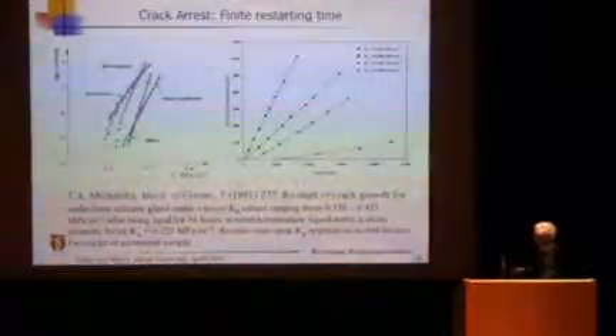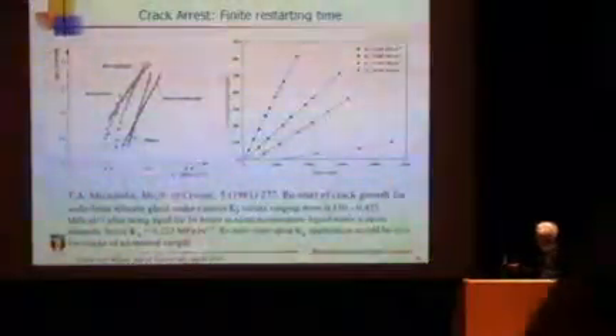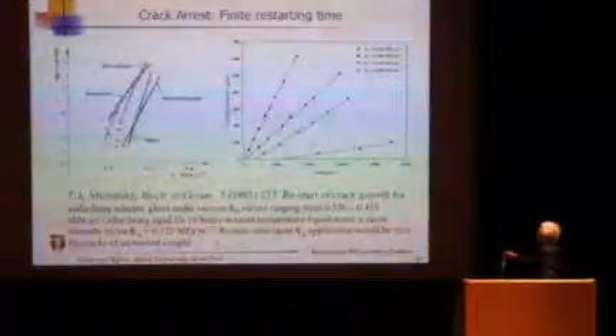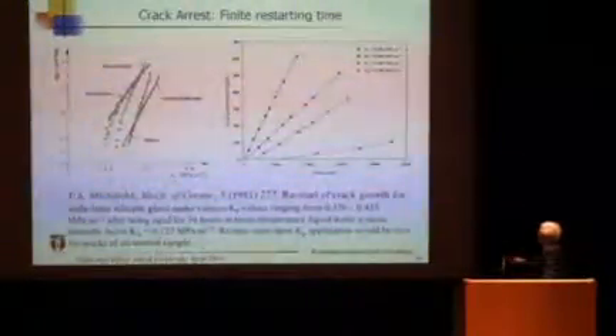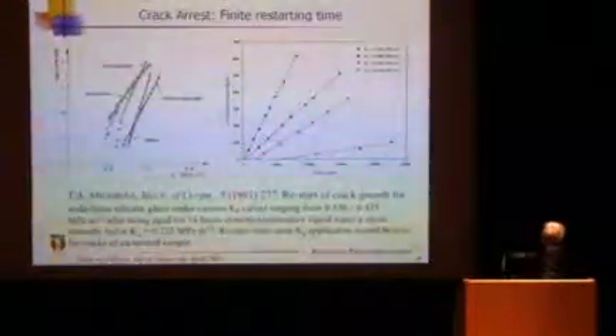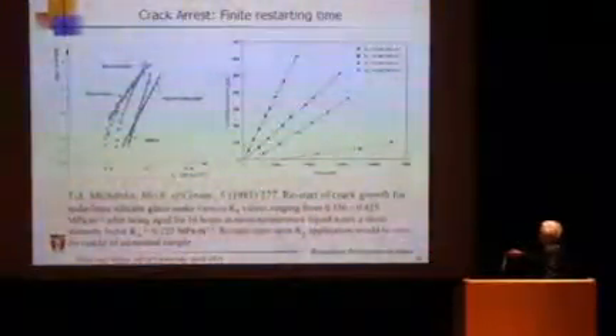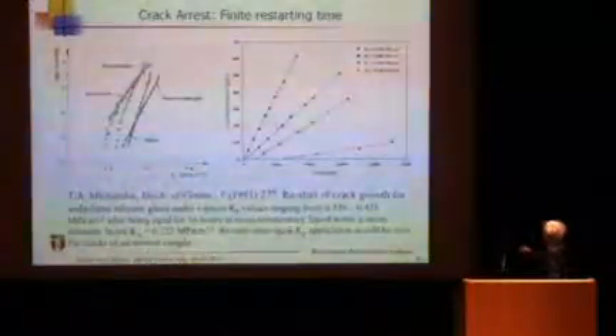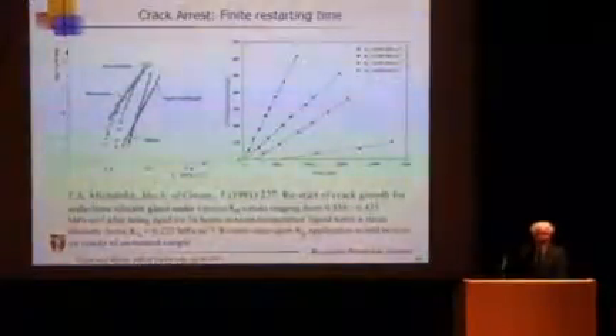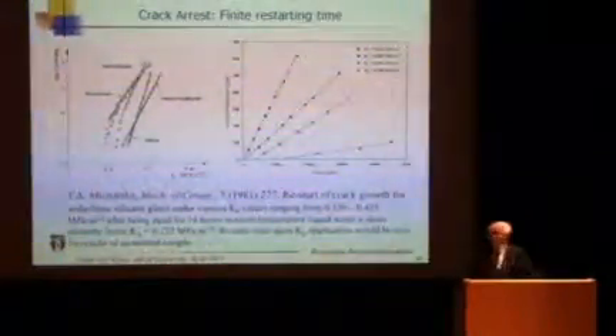So he took this glass and held it around here for a certain time, 16 hours at this point, and then brought it to higher stress intensity. And then he found the funny thing that if you go to here, you have to wait a long time before the crack restarts. If you go to a higher value, it started more quickly. So by the treatment here, this wait time was observed. That, again, is a mysterious phenomenon nobody can explain.